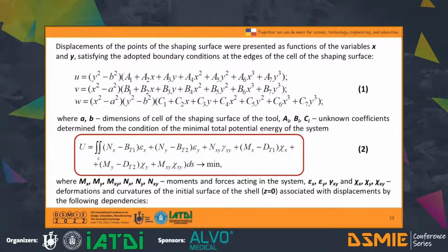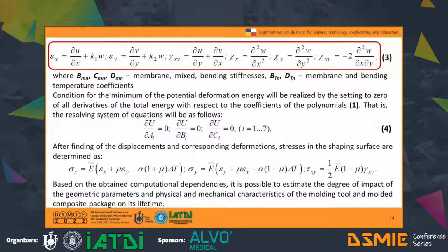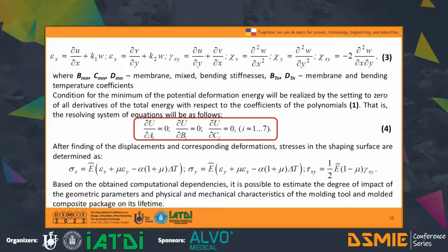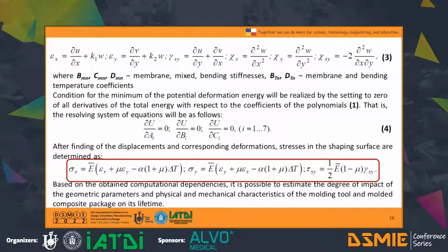Deformations and curvatures of the initial surface of the shell are associated with displacements by the following dependencies. The condition for the minimum of the potential deformation energy will be realized by setting to zero all derivatives of the total energy with respect to the coefficients of the polynomials. Stresses in the shaping surface are determined based on the obtained computational dependencies. It is possible to estimate the degree of impact of the geometric parameters and physical and mechanical characteristics of the molding tools and molded composite package on its lifetime.